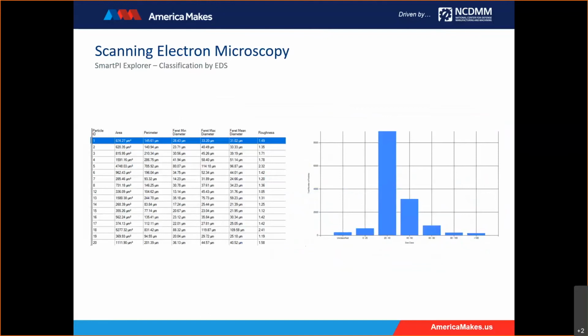At the end of the run, we want to get a table where each particle is labeled with an ID. The particle morphological features, such as the area, perimeter, diameter, roughness, are computed and populated in this table. And SmartPI also plots a histogram showing the particle size distribution of all the particles in the data set. So we can see if we have a normal distribution, bimodal distribution, or a lot of fines, which will of course affect our printing parameters.